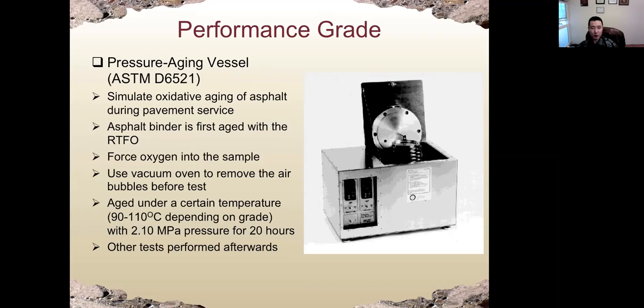So we use a vacuum oven to remove the air bubbles before the test, and then we age at a certain temperature. This is about 100 degrees Celsius, depending on the grade of asphalt. We also apply high pressure because we want to accelerate the aging process. So for 20 hours, we can simulate the aging process for 10 or 20 years of asphalt. Okay, and after that, we can do some other tests such as shear, creep, and other mechanical property tests.